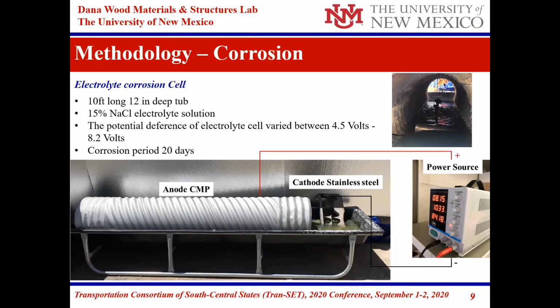The pipe was in the shape that would have been used directly in the annular space, but we decided to corrode it. The corrosion period we did for 20 days because that's an accelerated corrosion cell. You can see a picture on the right side or top showing inside the pipe, where we actually have a nozzle to spray. It was a movable nozzle, to make sure that the corrosion is spread over the pipe.